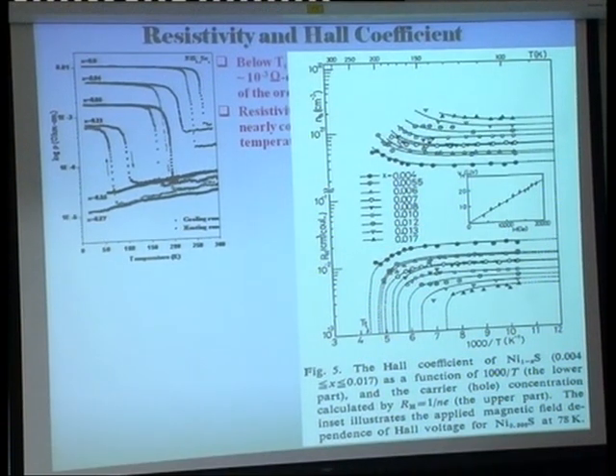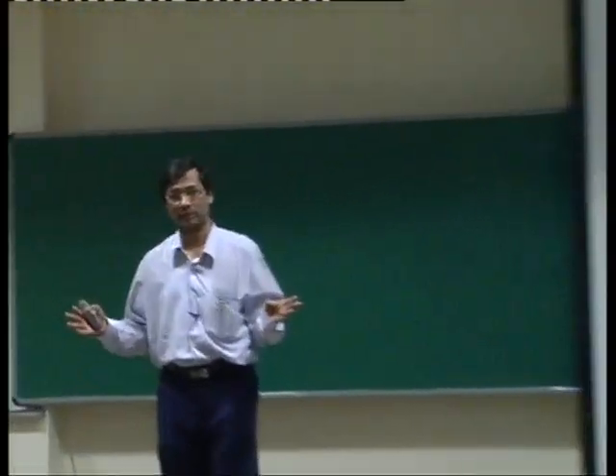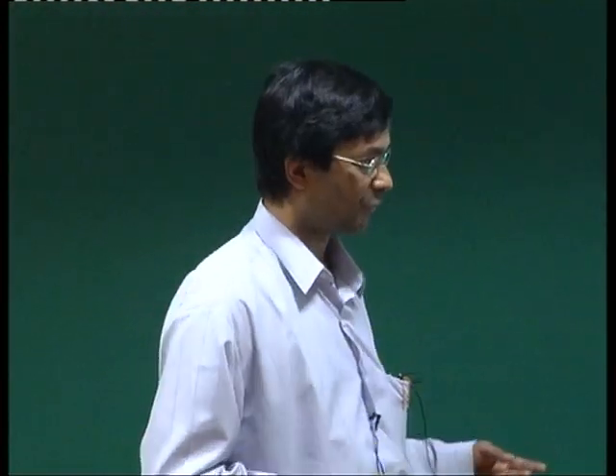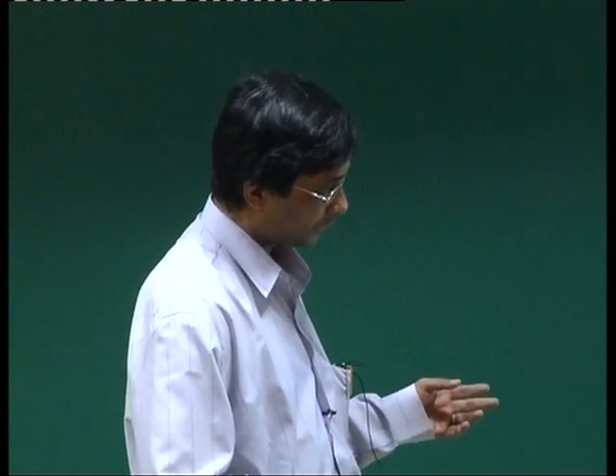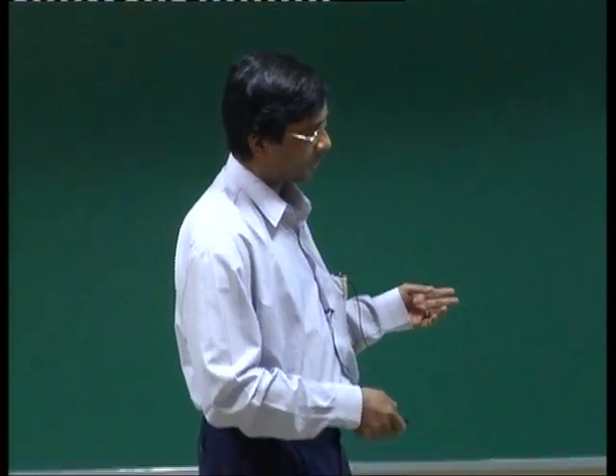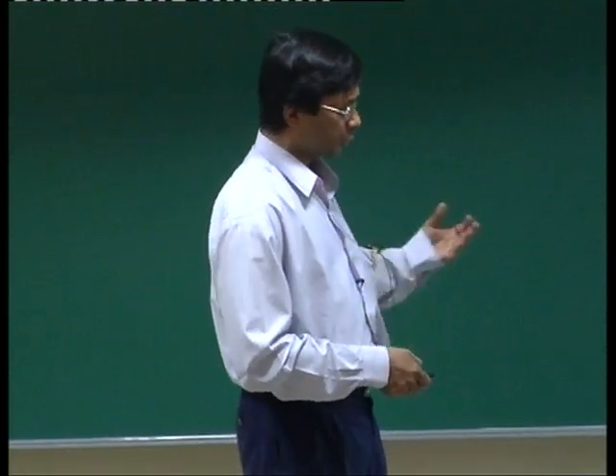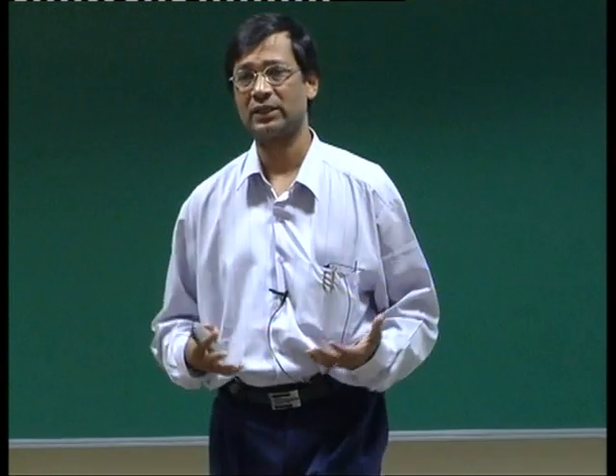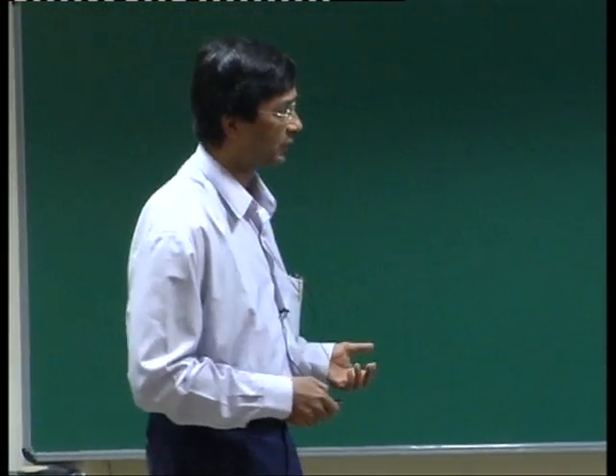If you're looking at the low temperature, most of the time I'll be talking about low temperature, because there's not so much controversy, there's more or less complete agreement about the high temperature phase. So you have to look at this part up there. In the high temperature phase, which is on this side, you can see that the RH drops down by approximately a factor of 40, showing that there's a lot more charge carriers, and that we're not interested in.